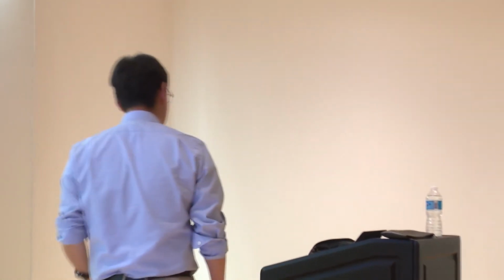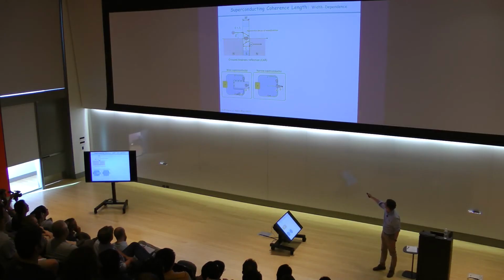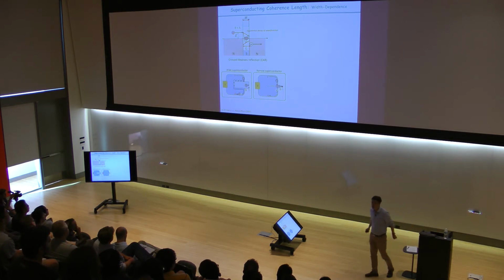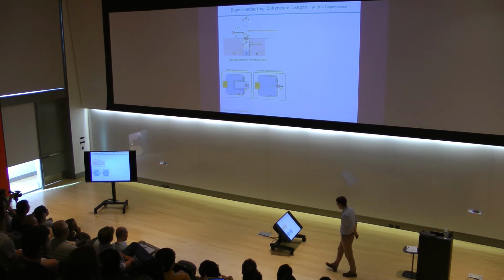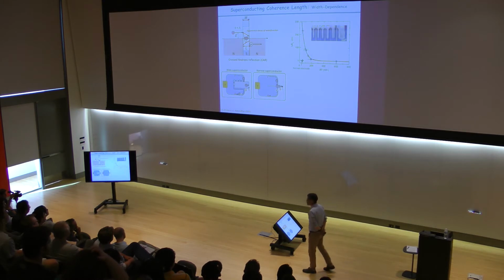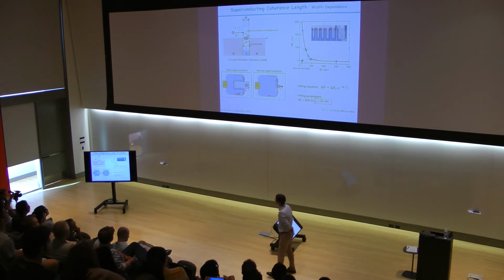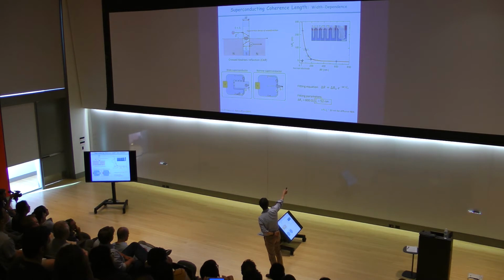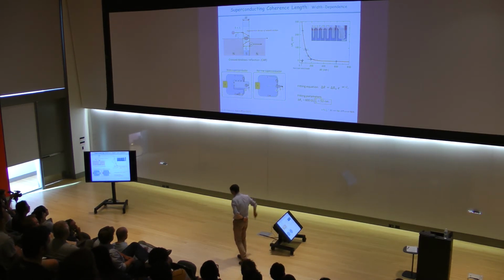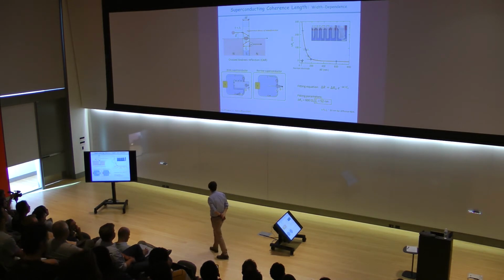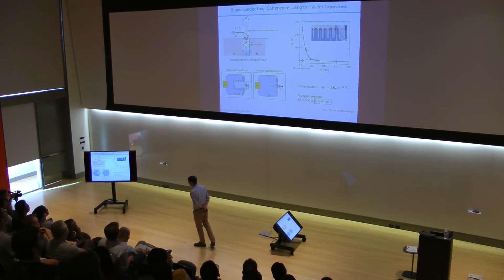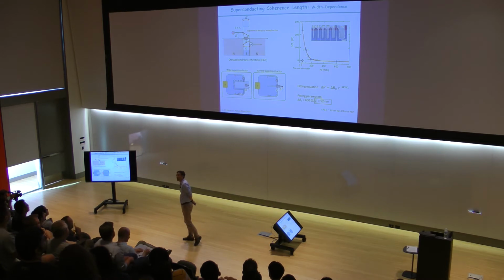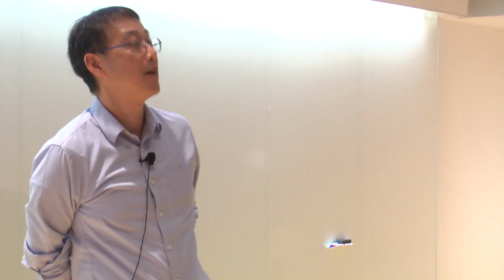In terms of the more complicated word, this is what you call the Andreev process, or especially the cross-Andreev process. It happens when you have a really thin superconductor, where the electron is allowed to turn into a hole across this very thin superconductor, thinner than the superconducting coherence length. That means that if you make the superconducting electrode thicker and thicker, we quickly lose the negative signal. This length scale tells us the superconducting coherence length in this system. So it has been nicely done, right? I mean, you may say, all right, I can see this, but why is this related to the so-called Majorana particle?